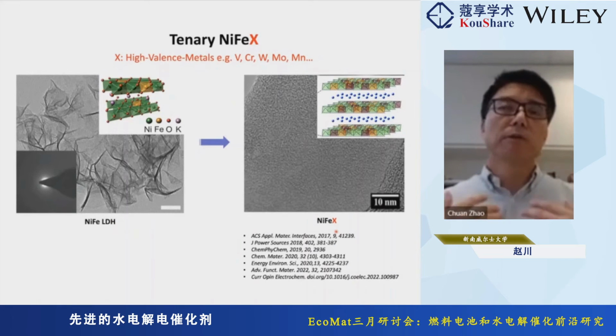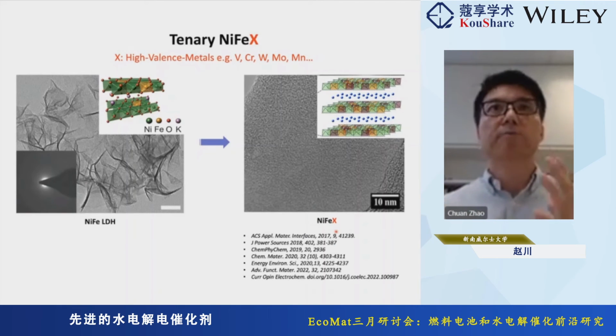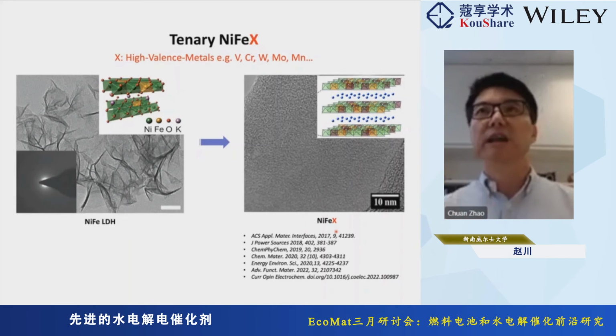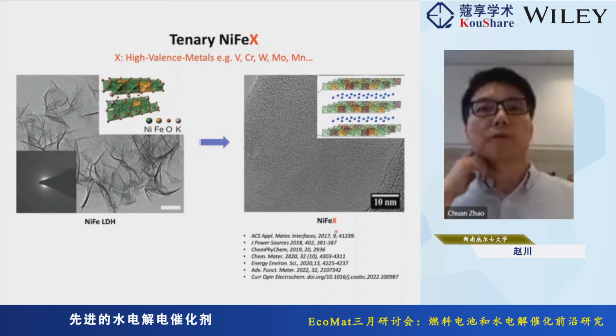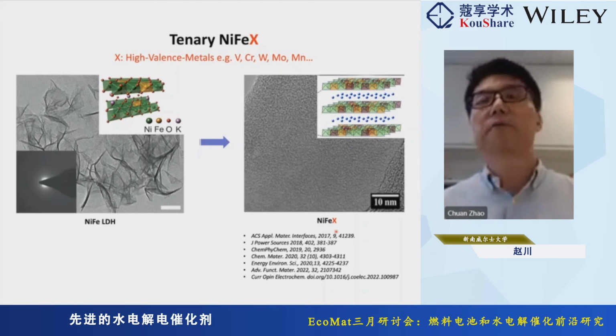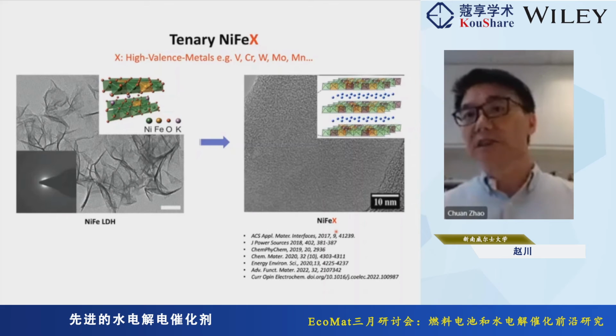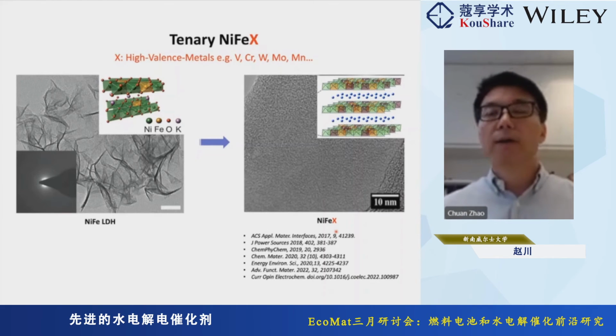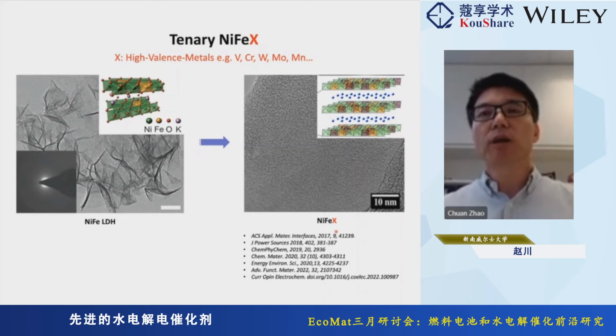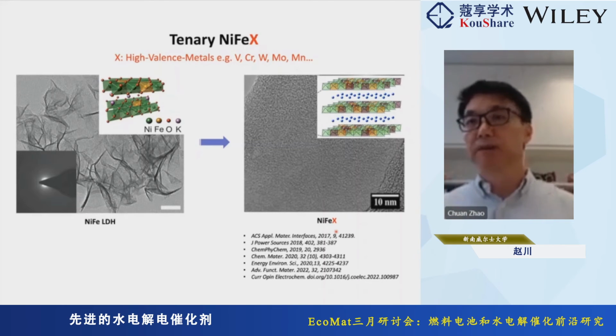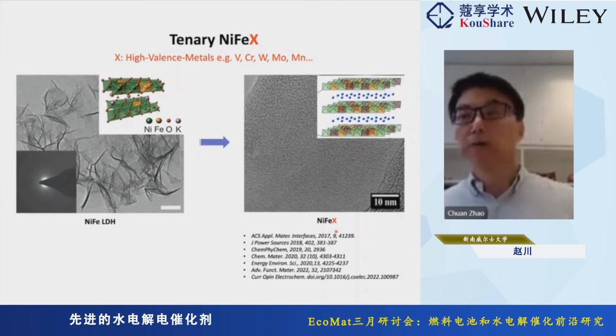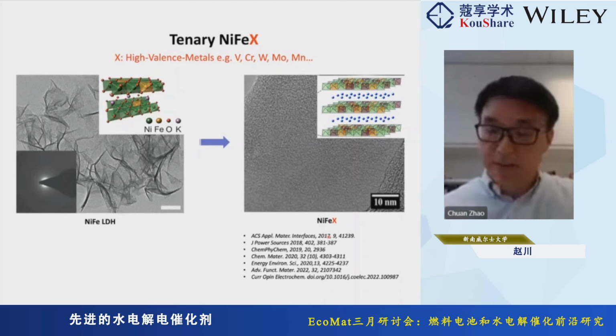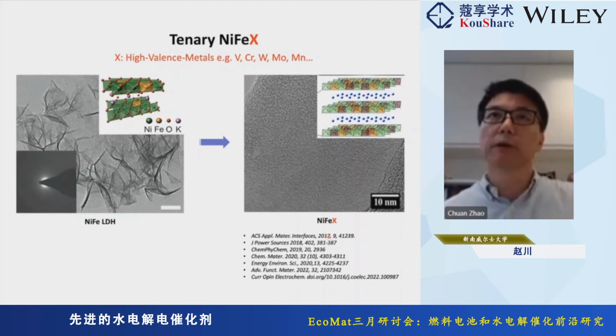More recently, we are also looking to introduce another metal into nickel iron, particularly high valence metals like vanadium, chromium, tungsten, manganese, molybdenum, all those different high valence metals, in order to lower the oxidation state and also the energy barrier for the oxidation transition of 3D metals like nickel, which is usually the thermodynamic limiting step for the OER.